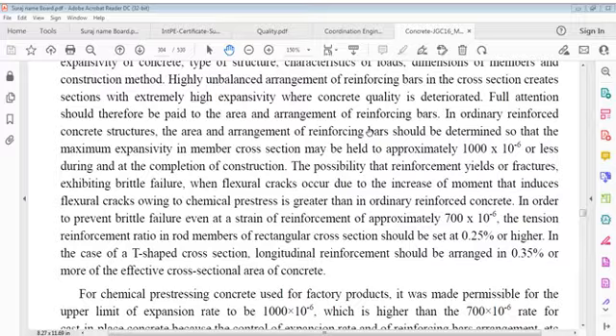and completion of construction. Possibility that reinforcement yields or fractures, exhibiting brittle failure even at strain of reinforcement of approximately 700 × 10^-6. Tension reinforcement ratio in members of rectangular cross section should be set to 0.25% or higher. In case of T-shaped cross section, longitudinal reinforcement should be arranged in 0.35% or more effective cross sectional area.